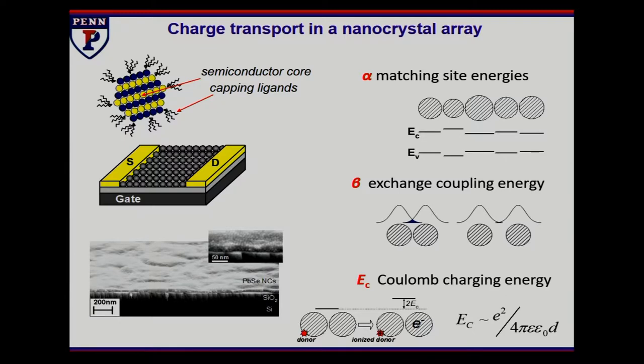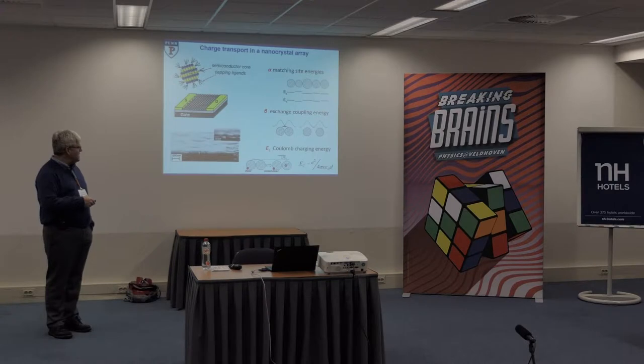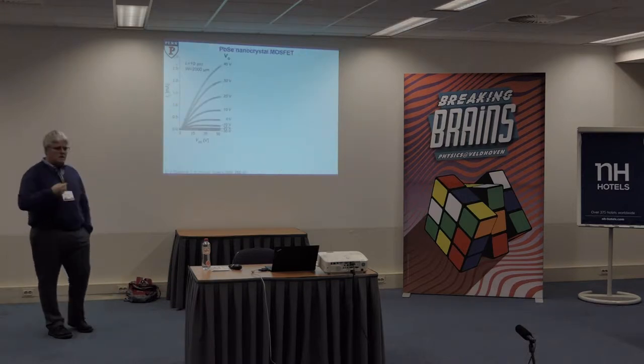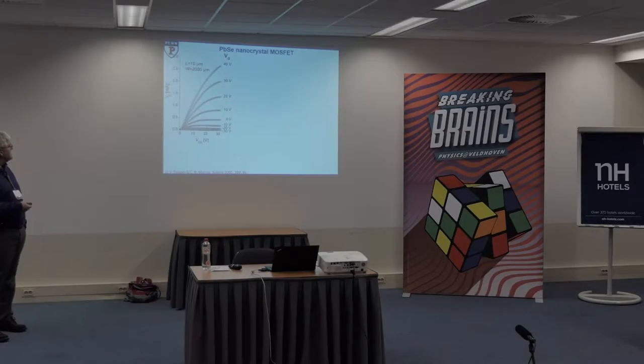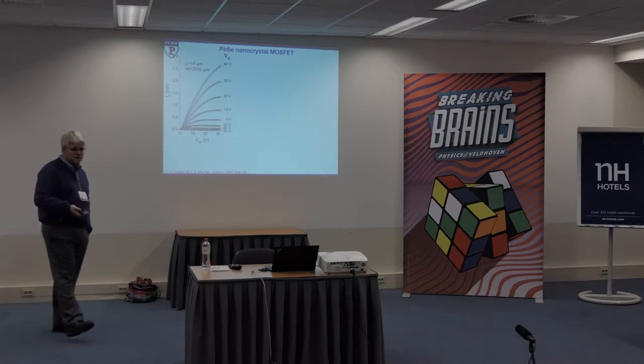But as we go through these, the matching of energy, alpha, the overlap between the wave functions, beta, and this EC, Coulomb charging energy, if we can optimize these, we can get to a state where we begin to get delocalized electronic behavior that looks a lot like a traditional semiconductor material. And so this doesn't look like a very good one necessarily. This has mobility of around 1, which means it's comparable to amorphous silicon.